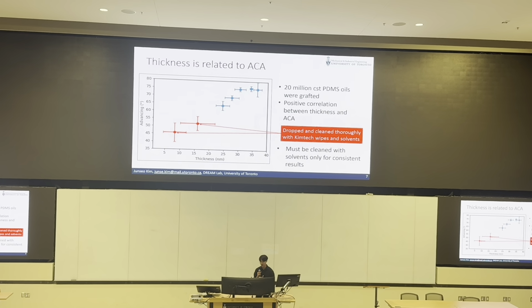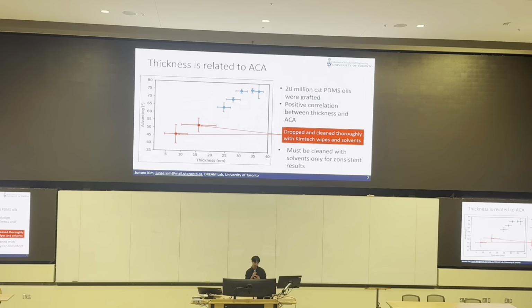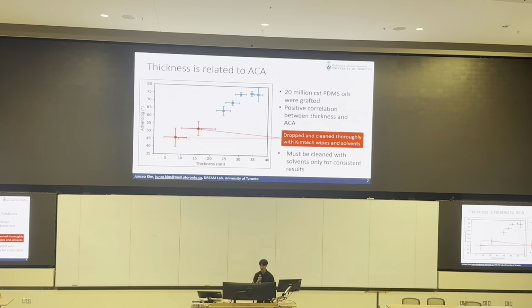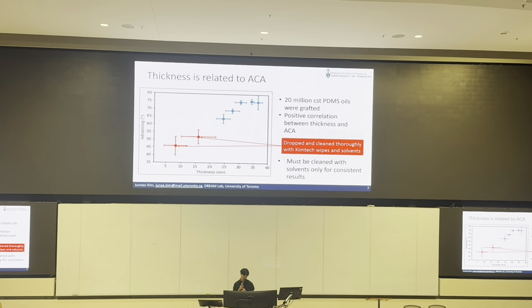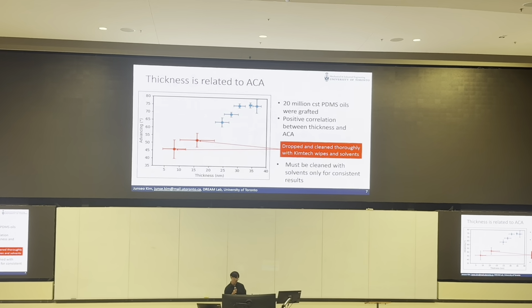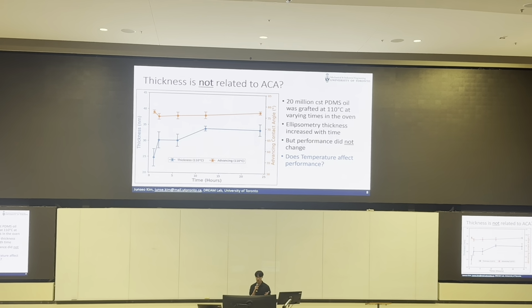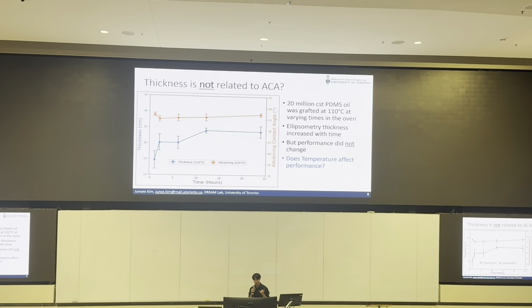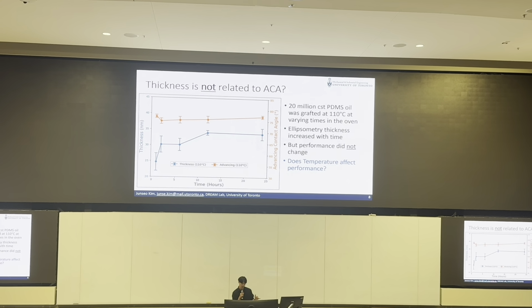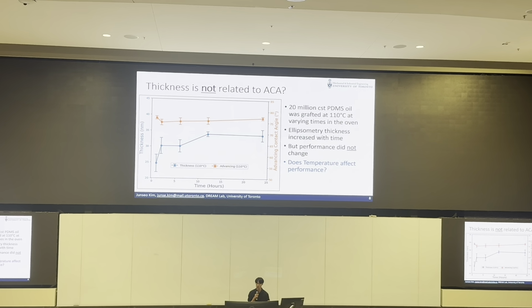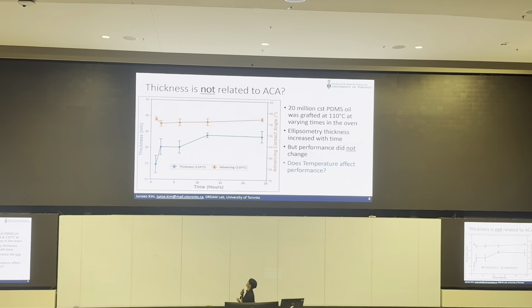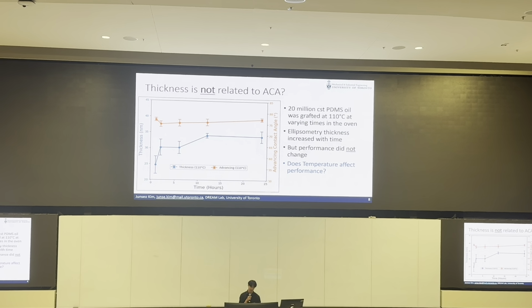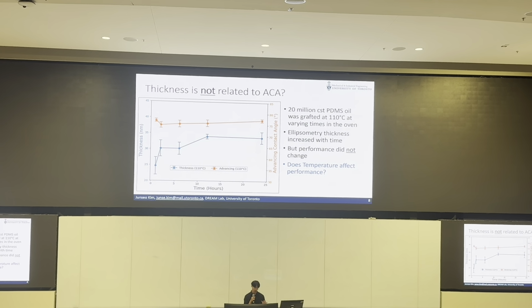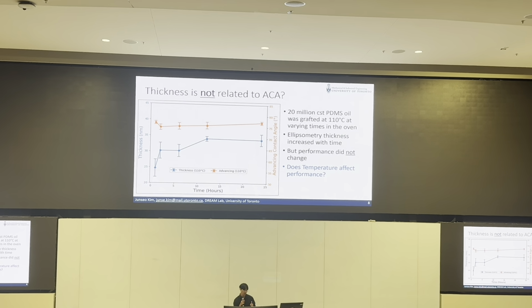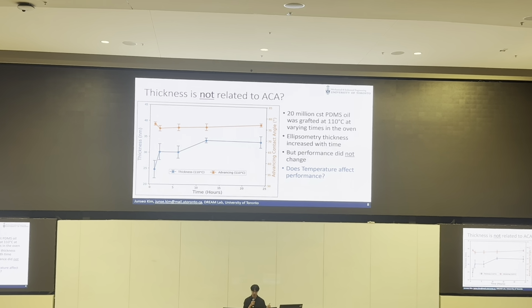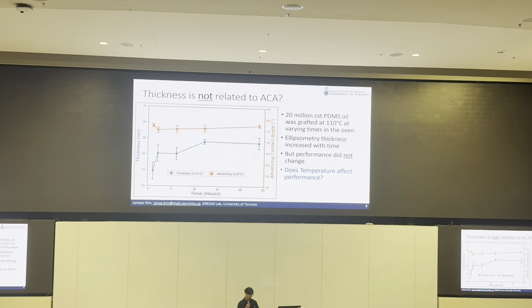So I stopped using Kimtech wipes completely, and instead of using those to clean my samples with solvents, I just used purely solvents and just submerged them. Once I started doing that, something interesting happened. What I found was that thickness was actually not related to the advancing contact angle. You can see this plot. The x-axis is time, which is curing time in the oven, as well as the thickness plotted on the left and the advancing contact angle on the right, those are the axes.